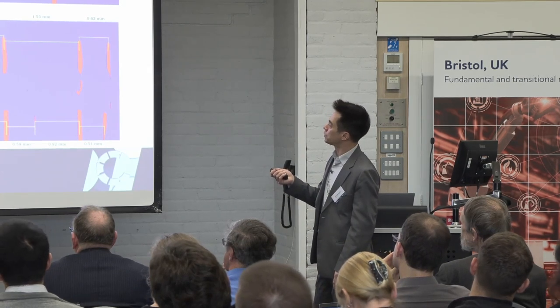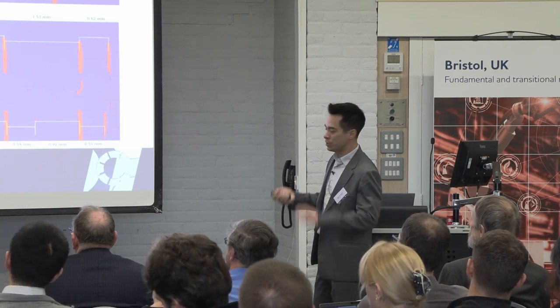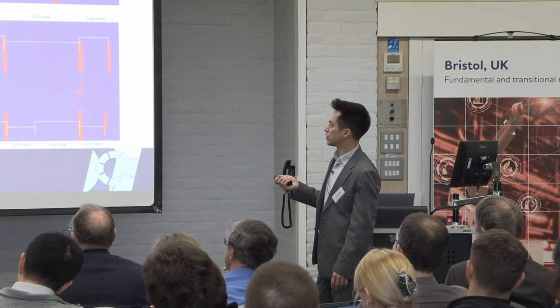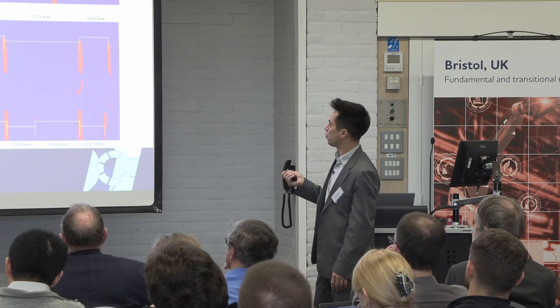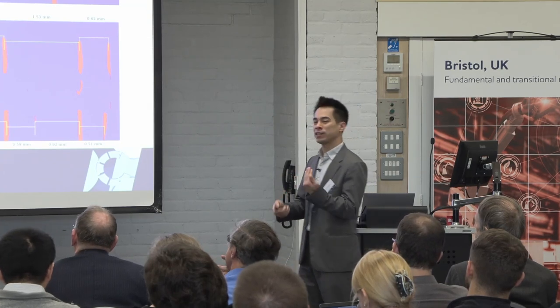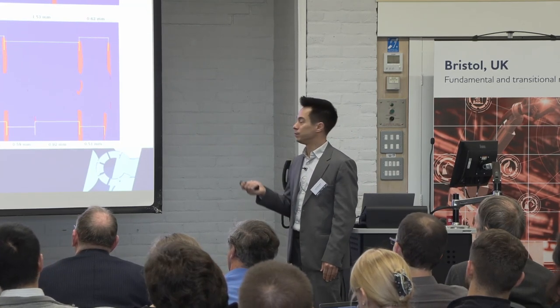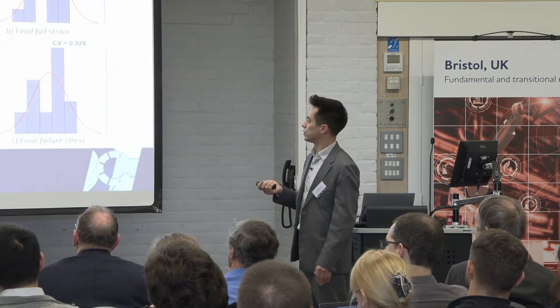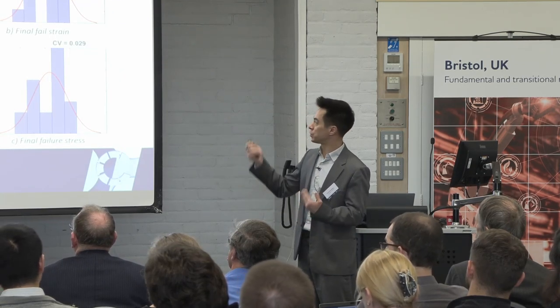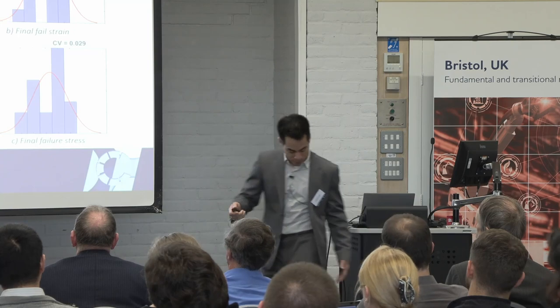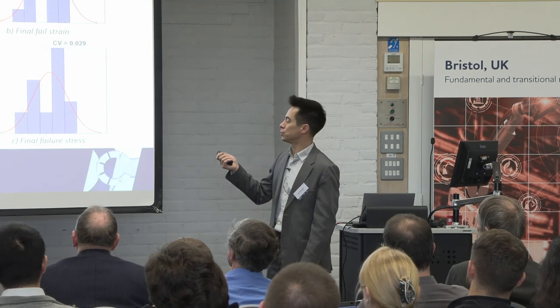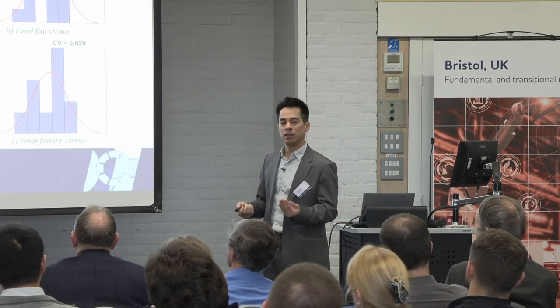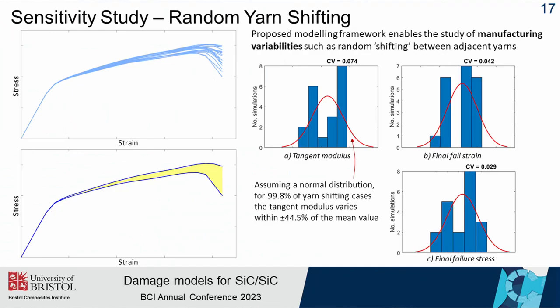One of the limitations of the model is that that continuous, very homogenized matrix doesn't allow for as many cracks to nucleate as it happens in real life. Okay? However, we're still happy with the results. And this modeling approach, just a couple of slides showing that the modeling approach could also be used to quantify the effects of variability in terms of manufacture. For example, if you have a random shifting of yarns and plies with respect to each other, we can get